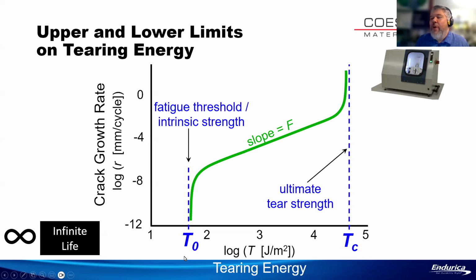For a natural rubber, for example, T naught has a value of something like maybe 50 joule per meter squared. And if you're below that, then the crack does not have enough energy to break any polymer chains, and so it doesn't grow no matter how many cycles you give it. And so the whole idea in infinite life analysis is, first we measure T naught, and then we calculate what is the margin between my worst case load, which is hopefully below T naught. What's the margin between that worst case load and T naught?